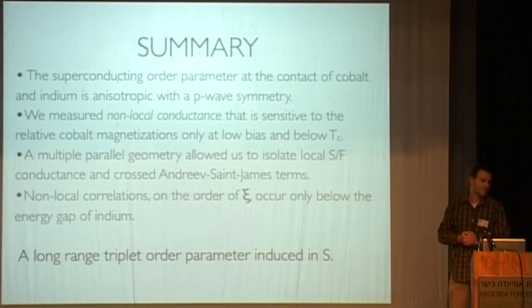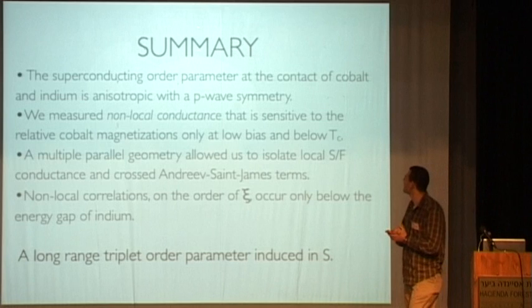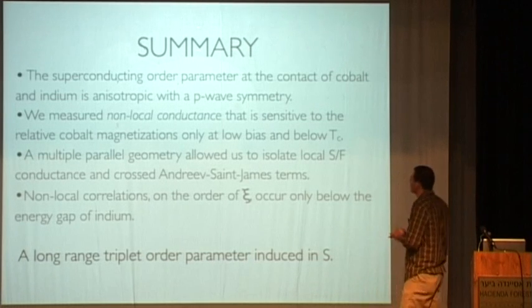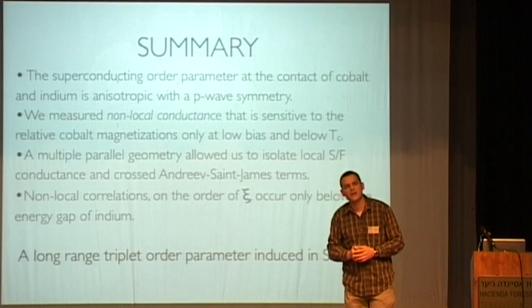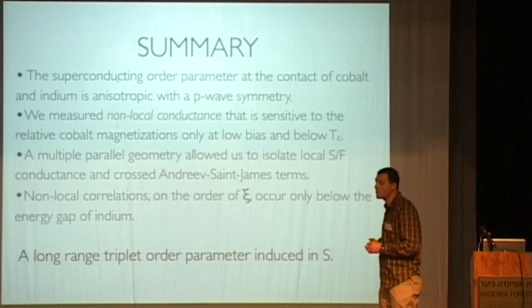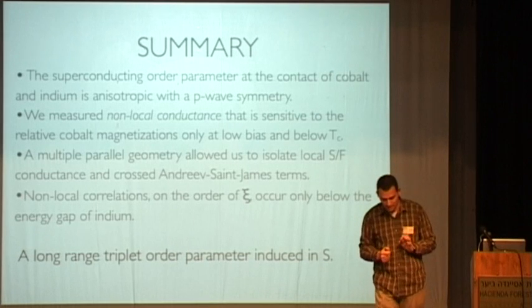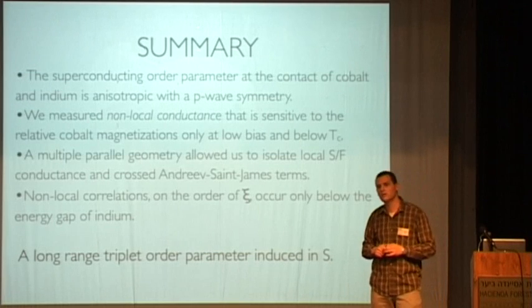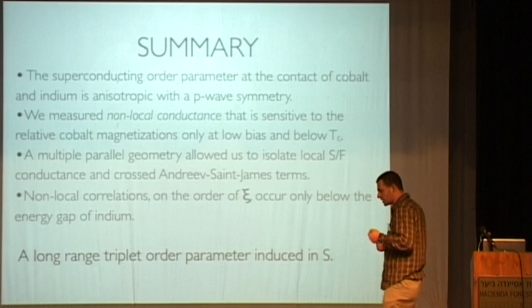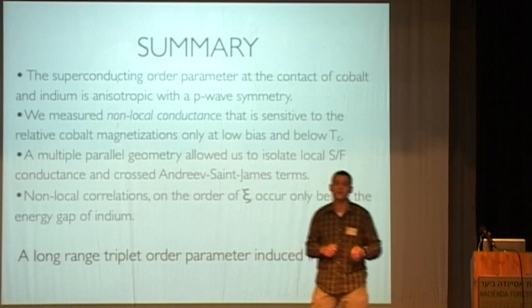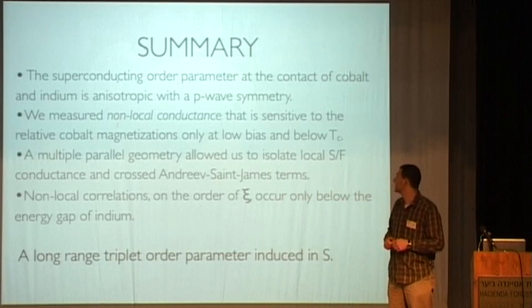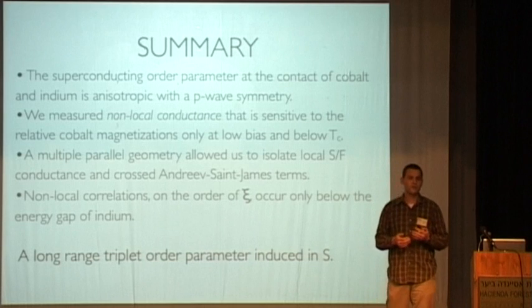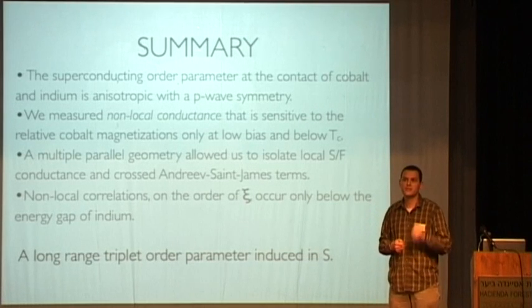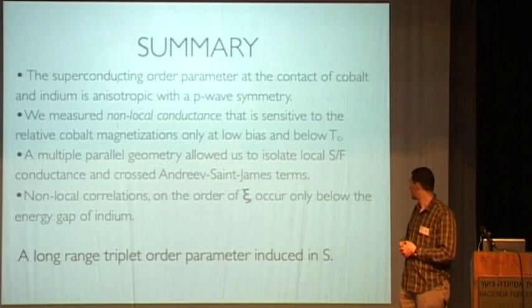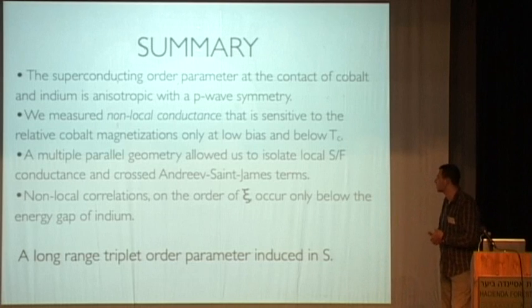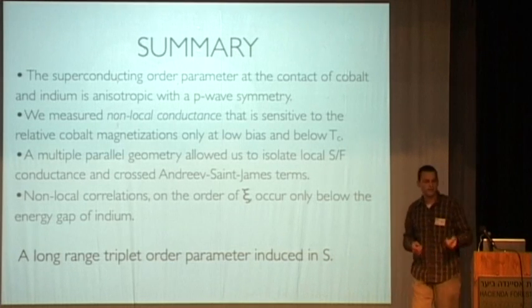So do I have time to summarize? So I showed you that the order parameter of indium and cobalt is anisotropic. I showed you that we measured non-local conductance. By the way, it's the first time that anyone was able to measure non-local conductance and show that it's really due to Andreev reflection, with energy spectroscopy in this conductance. And I showed you a multiple geometry that allows us to really distinguish between non-local effects. And the bottom line is that there is a long-range triplet order parameter inside S. Thank you.